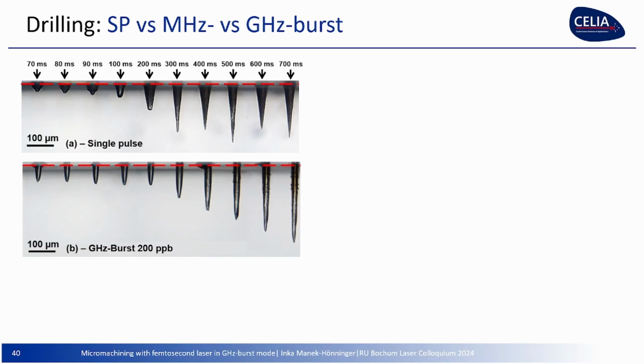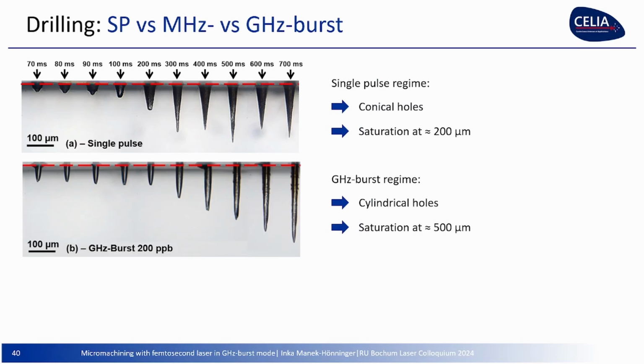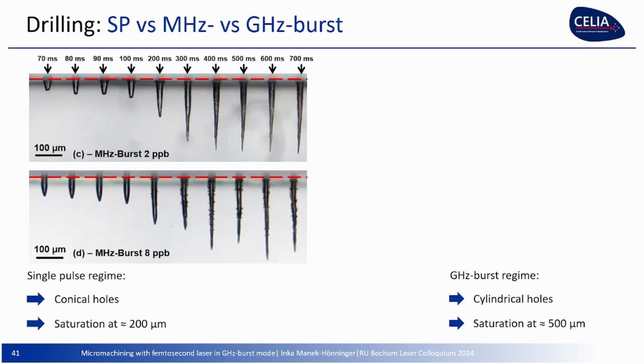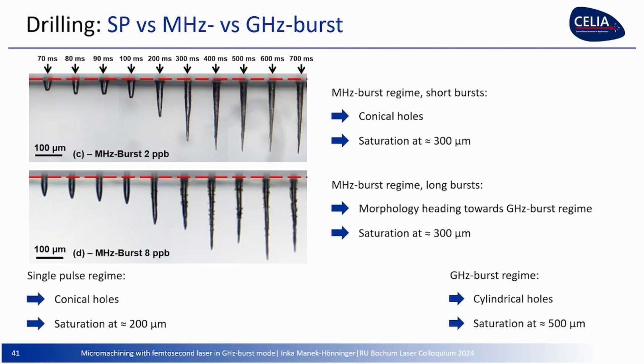So what do the holes look like? Here, single pulses, no surprise, they are conic, and in the gigahertz burst regime, they are more cylindrical. The saturation depth is not the same. When you go further, you go deeper. And if you compare megahertz with gigahertz, this is for 2 pulses. It's a mini burst, 2 pulses, a double pulse. And this is with 8. And you can see this is more like single pulses, and this has already a trend, especially in the beginning, somehow similar to the gigahertz burst regime. So you have these regimes, and in the megahertz burst regime, short bursts are more like single pulses, and long bursts are more like gigahertz. Not really surprising.